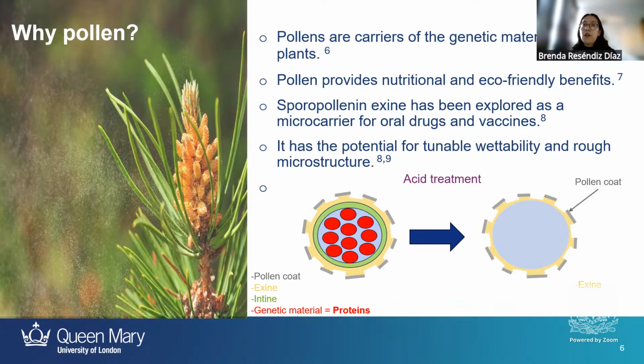So to try to improve hydrophobicity, we need to remove those proteins from the pollen. So we use an acid treatment to remove all those proteins, so we can keep just the pollen coat, which is hydrophobic, and the exine layer, which is going to give you the rough structure.